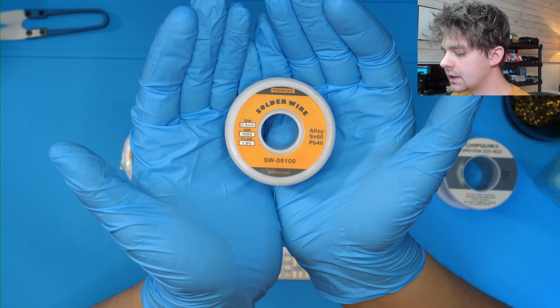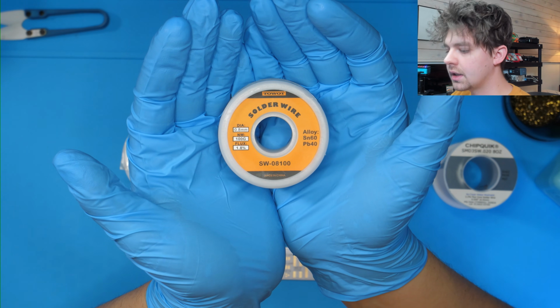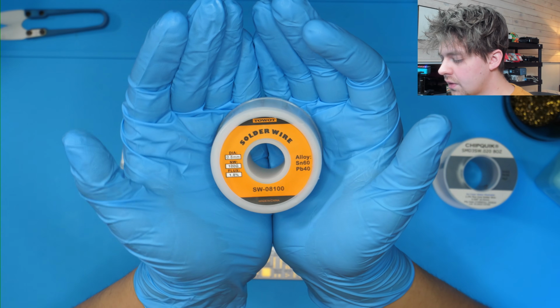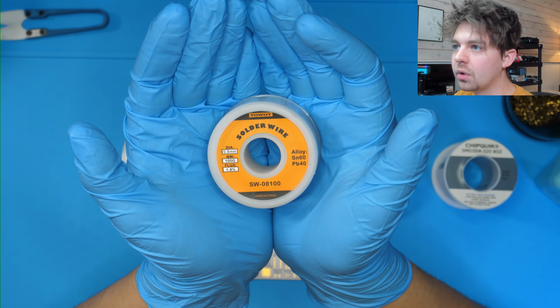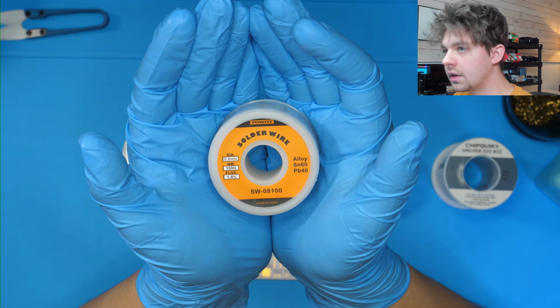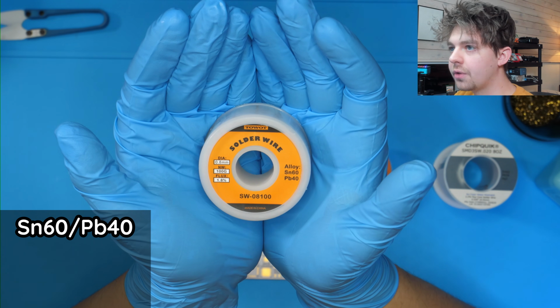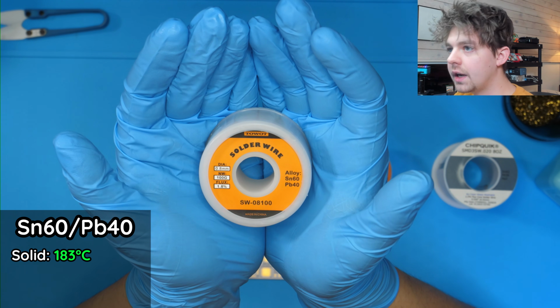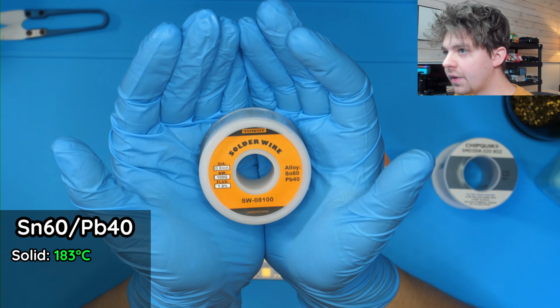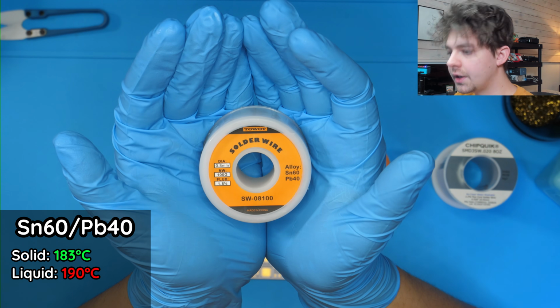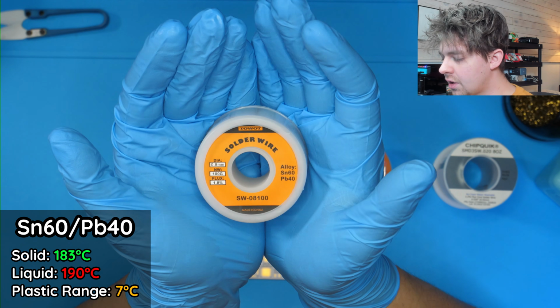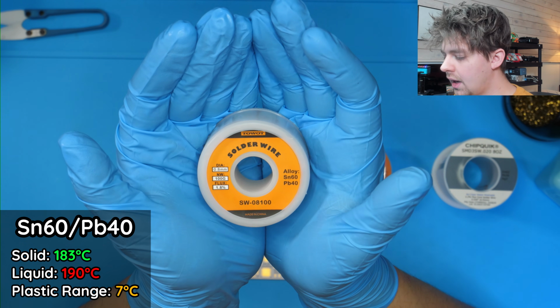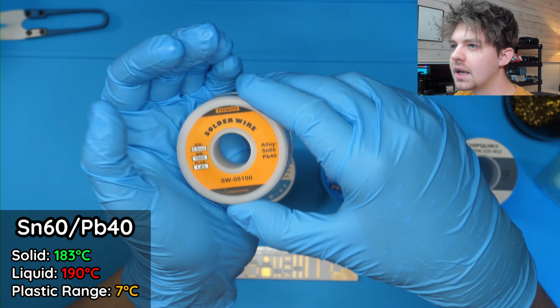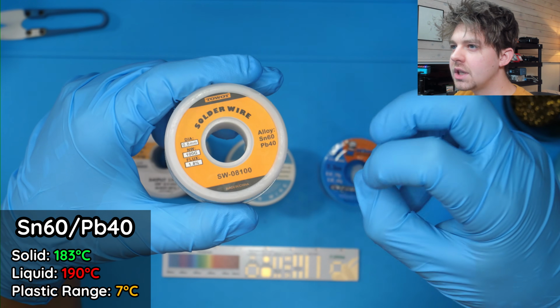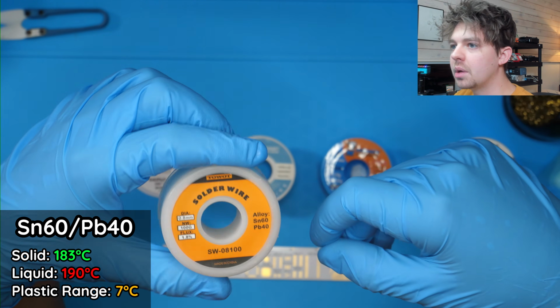I personally don't like this stuff because it is not eutectic. What that means is there's a small temperature range with this stuff where it is in between a fully liquid state and a fully solid state. So 60-40 solder is generally fully solidified at around 183 degrees Celsius, and fully liquefied or melted at around 190 degrees Celsius. So there is that 7 degree Celsius range where this stuff is in between states, and it makes for this weird mushy state that I'll definitely show you in a moment.